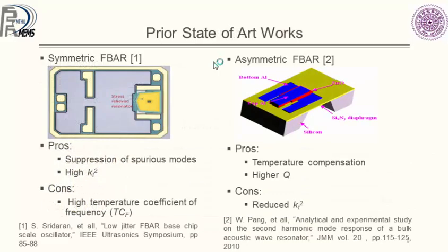Moving on to the review: the first design is the symmetric F-bar used by Avago. It has a piezoelectric layer sandwiched between two electrodes. The advantage is separation of even harmonics and a higher kT-squared coupling coefficient, since the device response is dominated only by the piezoelectric layer. The disadvantage is that the temperature coefficient is not that good.